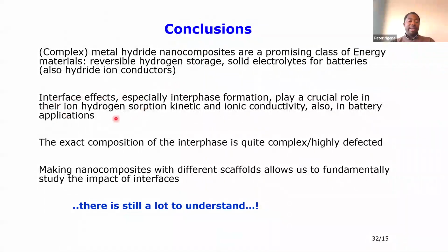Also for catalysis, I didn't show a lot here. Basically, interface effects, especially interphase formation, play a crucial role not only in hydrogen sorption kinetics but also in ionic conductivity. Also in battery applications, I didn't show how making these nanocomposites leads to better battery performance. The exact composition of the interphase is quite complex. It's a highly defective phase, so we are trying to use computational models to figure out what exact composition is giving rise to the improved performance of our material.